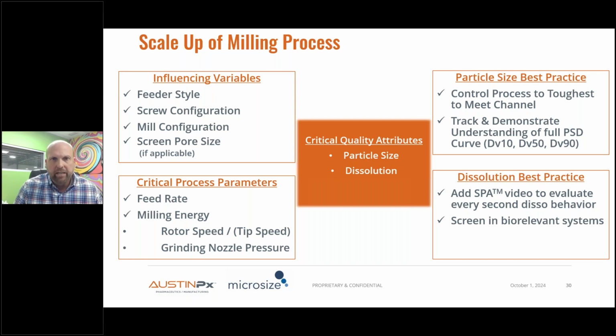We can watch every second, and every polymer system and ratio of API to polymer, depending on those properties and the polymer selected, as that dissolves and that surface area dissolution versus pore size dissolution. We can watch polymers swell or gel or linearly dissolve, as one would expect, but really use that knowledge to characterize and drive the formulation choices.